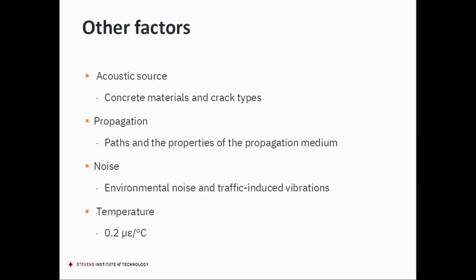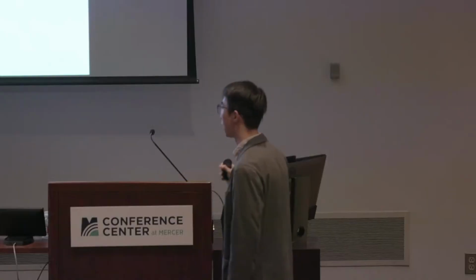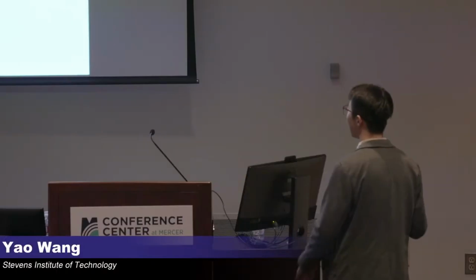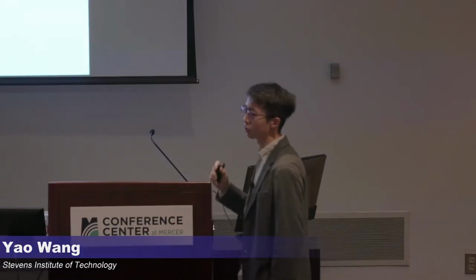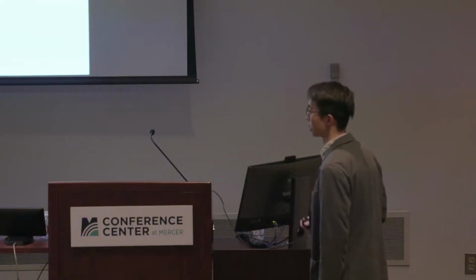And the last one is the temperature, which is also very important. Here I have shown that in the previous literature, researchers have found that when the temperature changes by 1 degree Celsius, the DAS signals will change about 0.2 microstrain, which is really high compared with the cracking signals. However, it's also easy to deal with.